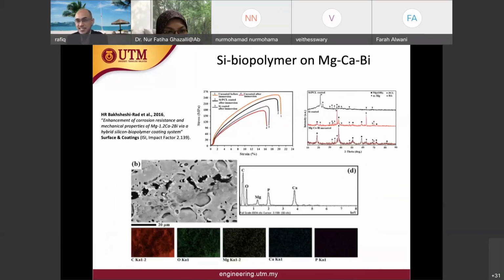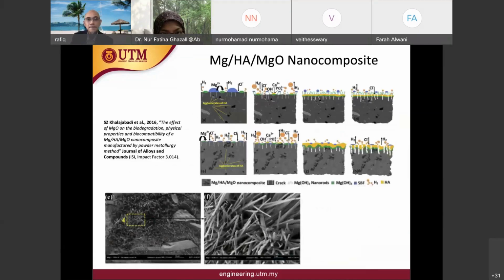Another work on magnesium calcium bismuth alloy. Now this time around we use silicon biopolymer coating to coat this magnesium calcium bismuth alloy. Another research work on magnesium. This one is magnesium hydroxyapatite magnesium oxide nanocomposite. And we see the effect of magnesium oxide on the biodegradation, physical properties and biocompatibility of magnesium hydroxyapatite magnesium oxide nanocomposite manufactured by powder metallurgy.